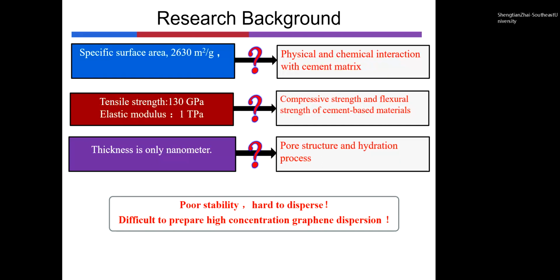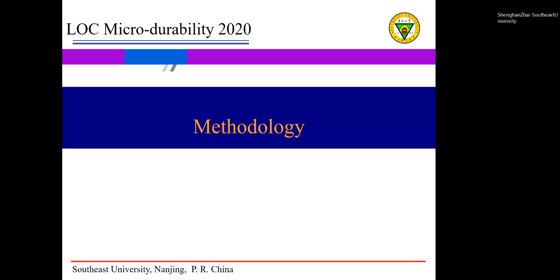However, the dispersion and the stability of the graphene in cement matrix are poor. Dispersion of the graphene in aqueous system, preparation of high concentration and stable graphene dispersion are the key factors for the development of graphene cement composites. Therefore, different dispersants and different ultrasonic methods were used to prepare the graphene dispersions in this study. Finally, the best dispersant and the most suitable ultrasonic method were determined. Next, please look at part 2.